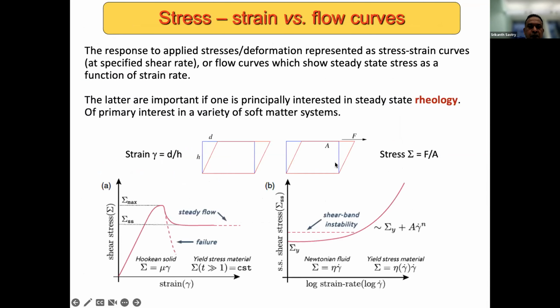Okay, before I continue, I'm essentially going to be talking about mechanical behavior as represented by the left bottom curve here, where I'll be looking at stress as a function of strain. But what this figure shows is that if one applies a large enough deformation beyond the yielding point, which is visible through a drop in the stresses beyond a maximum value, one settles into a steady flow regime, and correspondingly there is a steady state stress.